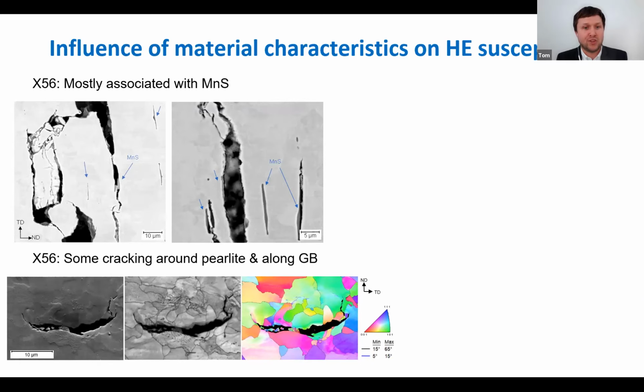We talk about hydrogen-assisted cracking when it's combined with mechanical loading. In this case, it's hydrogen-induced cracking because there is no mechanical load. It's only exposure to the hydrogen atmosphere that already leads to cracking without any additional mechanical loading. Here you can see cracks starting at inclusions, also at pearlite or along grain boundaries for the X56.